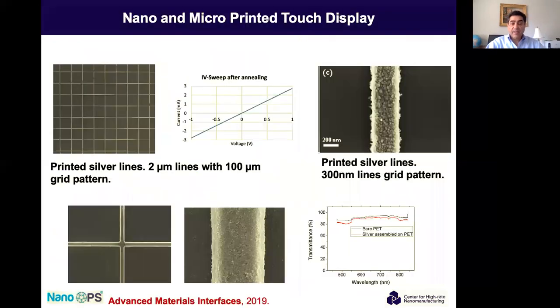We were also challenged by a company that works with Apple and makes the touch display for the Apple iPhone. The Apple iPhone has a geometry just like this one. It's 2 micron lines with 100 micron spacing. Some of them have 200 micron spacing. So they challenged us to print it on a flexible substrate. Apple prints it on a flexible PET substrate that goes under the glass, the Corning Gorilla Glass that's on your iPhone. So we took a PET substrate, we printed this, and we showed that it's transparent. This is the change in transparency. You can see it's about 2-3% transparency loss total.